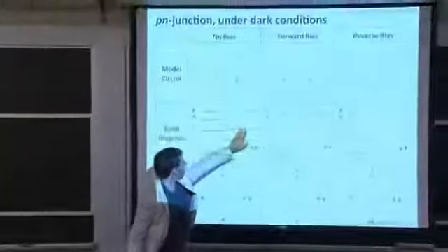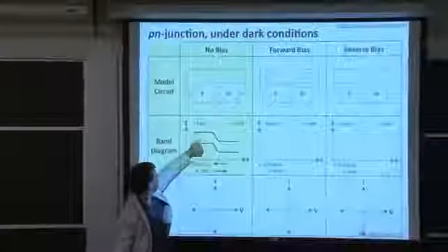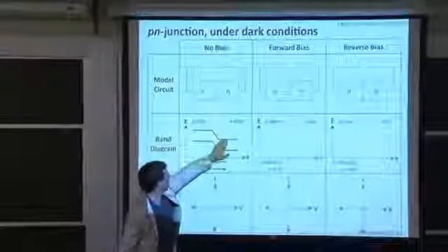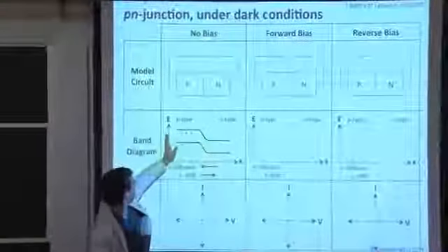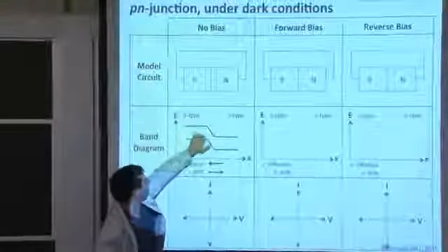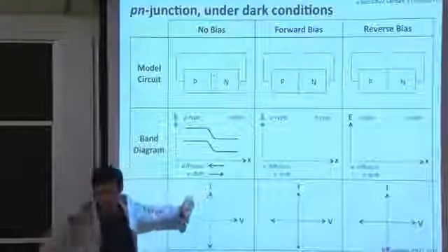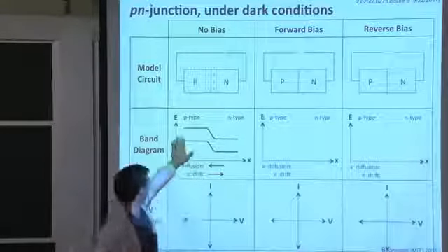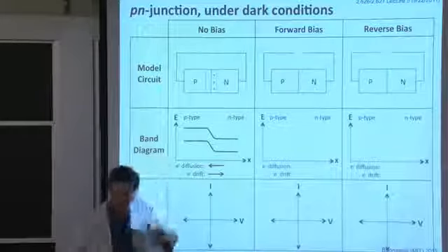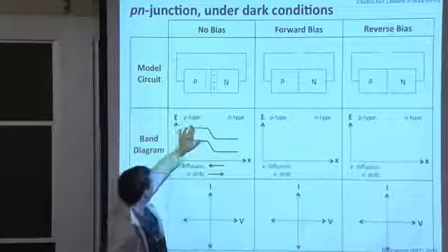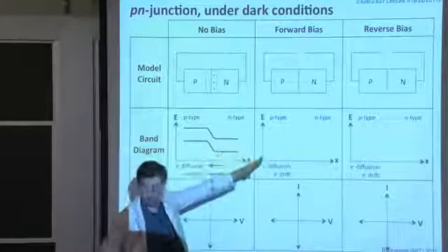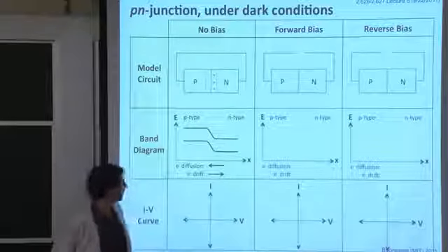The correct answer is, indeed, we have the band bending down like this. So we would have the bands higher on one side, lower on the other. The electron energy is higher on the p-type side than the n-type side. So if we add one electron to our system, for example, a photogenerated carrier from one photon coming into our device, that electron has the natural tendency to go onto this side, and will be swept down.